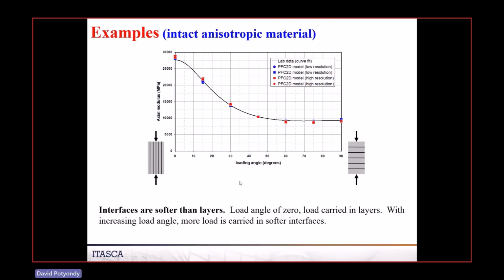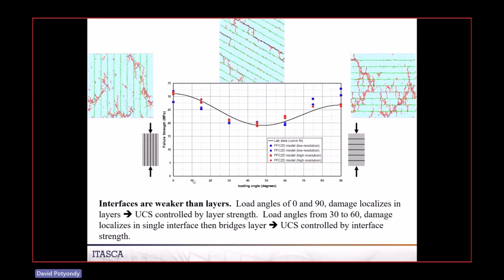The result then is the variation of both. This is modulus with loading angle. So when it's loaded this way, it has a high modulus. But when it's loaded this way, since these interfaces are softer, you're measuring that stiffness. And this is comparing with lab data for this particular argillite. So that's the modulus variation, but you're also getting the same sort of strength variation. This is the UCS versus the loading angle. You can build simple theoretical models of these things, and you see this same sort of curve. Once you get to a 45-degree angle here, you start getting failure along the interfaces, which just makes it weaker. But then when you're like this and like this, you're getting failure in the intact material, which makes it stronger. So this seems to, again, make sense.